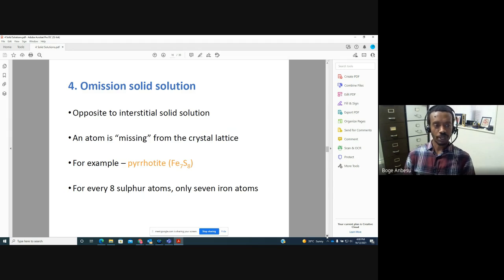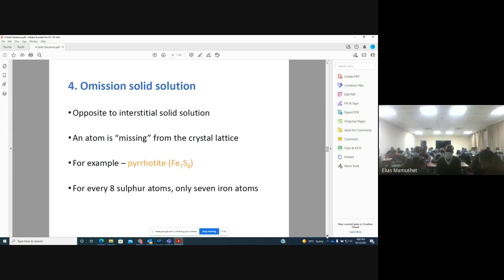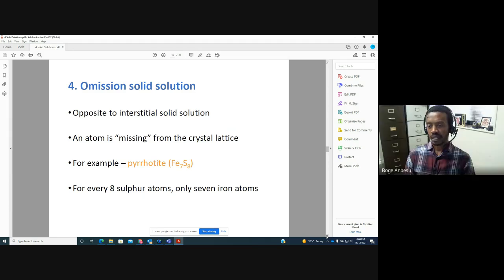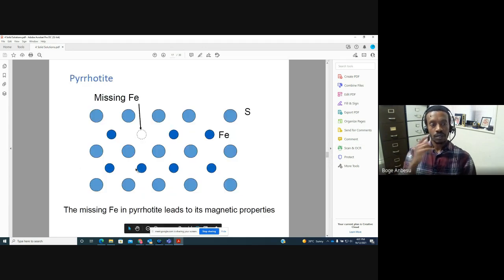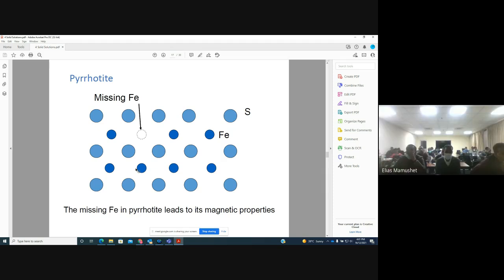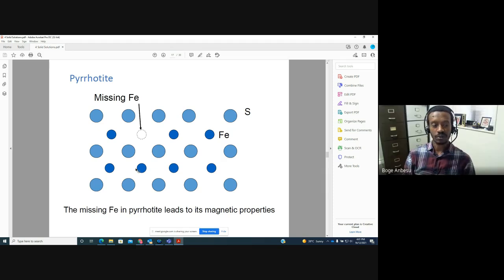The last one is omission. This is the opposite actually. Instead of an element occupying a space, there is an element missing from the crystal lattice. If you look at pyrrhotite, in pyrrhotite we have 7 iron and 8 sulfurs. So there's 1 iron missing for every 8 sulfur. It's probably better to see it in this depiction here. You can see there's 1 iron missing there. And we call this omission solution because there is some iron omitted from the crystal lattice.